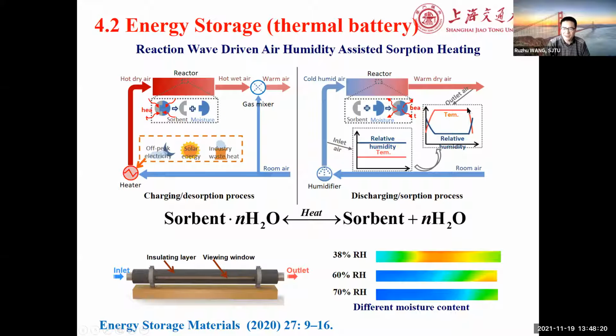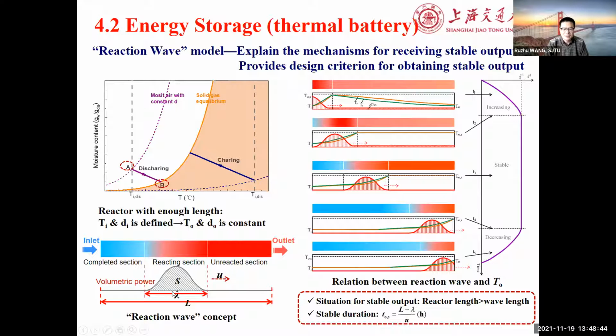In this case we created a new model, but more important is that if we develop this model to give warm, dry air at about 40 degrees centigrade or 35 degrees, it's good for heating. We did some research tests about this work and also generated a model, a so-called reaction wave model. What we found is that it has a wavelength and a velocity for the movement of the wave, which sets the design length of this kind of bed.